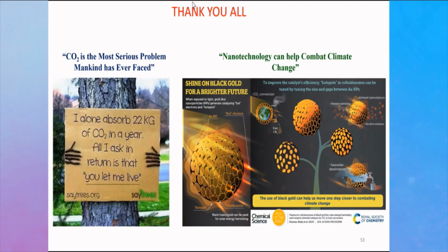Sorry. Dr. Lalit Prasad: how much amount of nanocatalyst is required to convert how much volume of CO2 into methane? I already showed you a different experiment, like for a depleted silica, we got around 4,000 micromole per gram per hour. For gold, this was very low, just 2 micromole. But obviously, gold was done with water at room temperature. The other reaction was done using external hydrogen, and at 400 degrees Celsius. So one has to look into that before you compare the different catalysts.